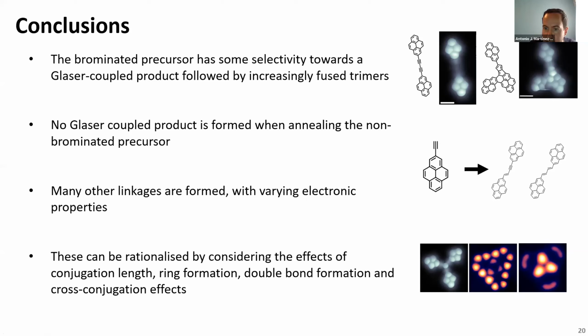Okay, next question is from Jorge Lobo. The Glaser coupling appears to be really inefficient compared with the Ullmann. Do you think that adding a bromine on the triple bonded carbon would reduce the zoology of the structures that you form, since you should be reducing the temperature of reaction? Yeah, definitely. It's been shown that you can add bromines on the end of these alkynes to form a Glaser coupled dimer. And if we didn't have the bromine on the side, of course, we wouldn't have all the different possible reactions that are related to Sonogashira coupling as well. So we reduce the amount of coupling possibilities that way as well. And it occurred at a lower temperature too. So yeah, he's right.